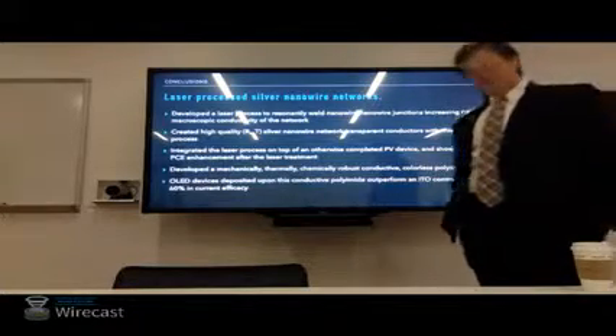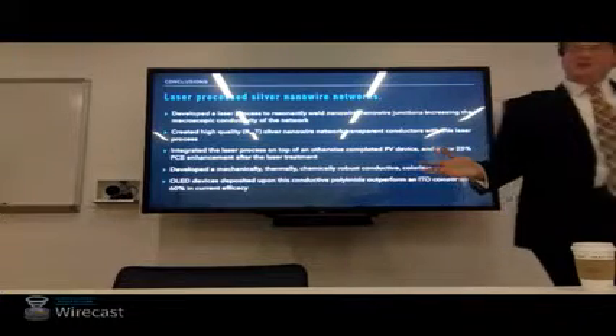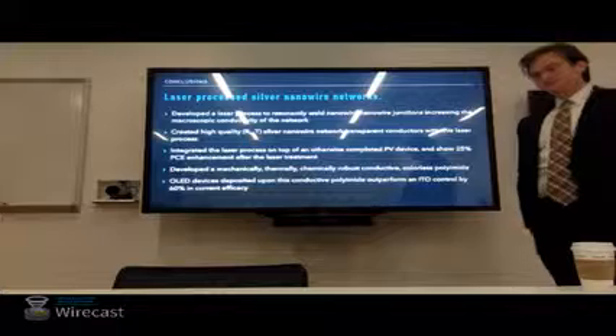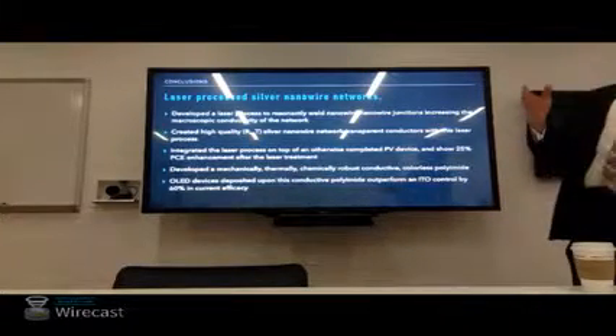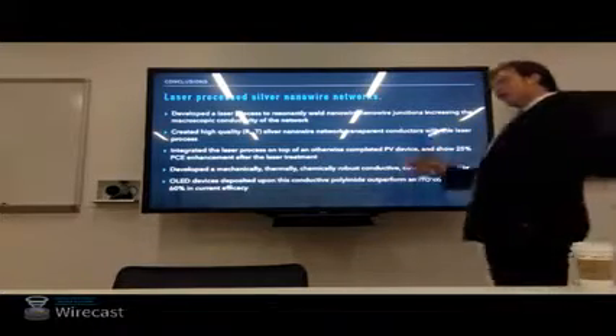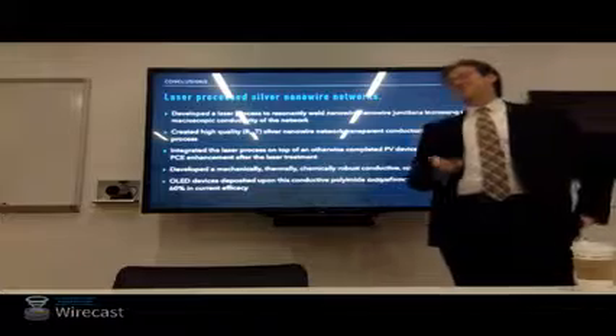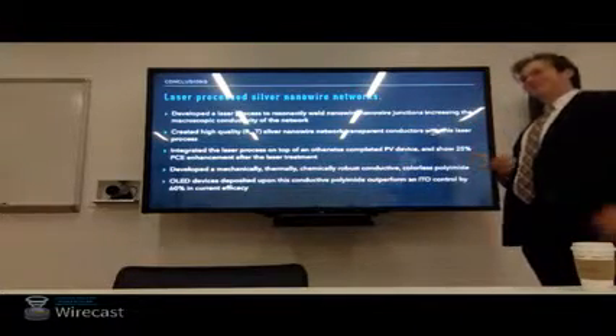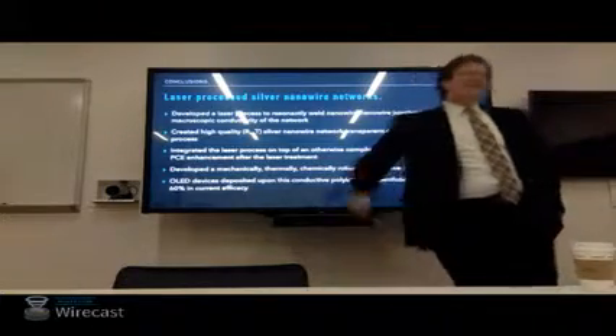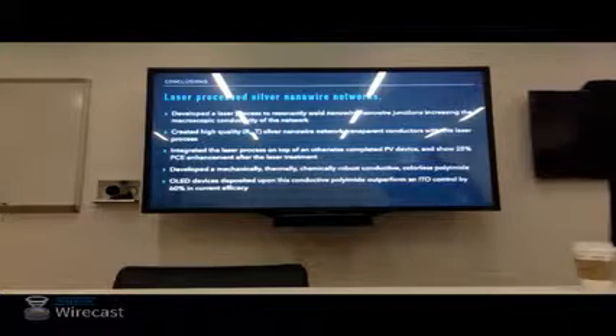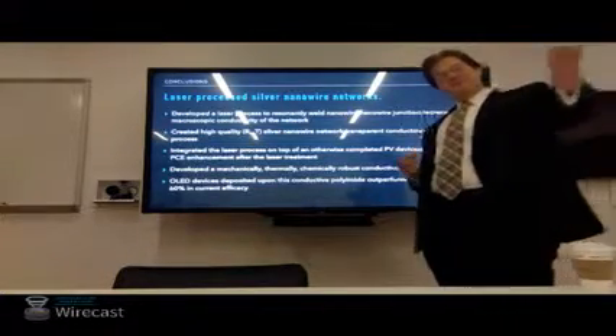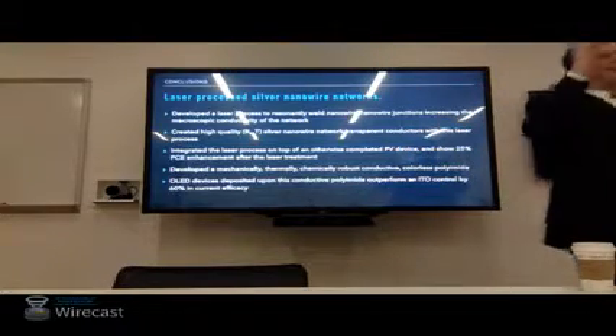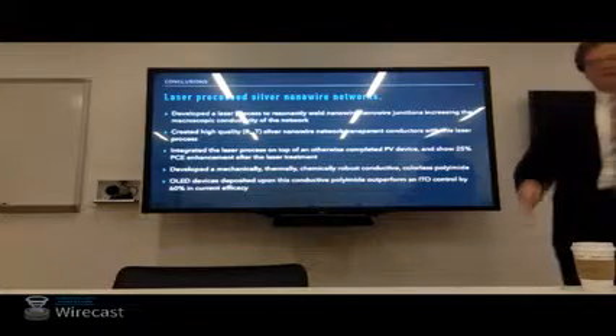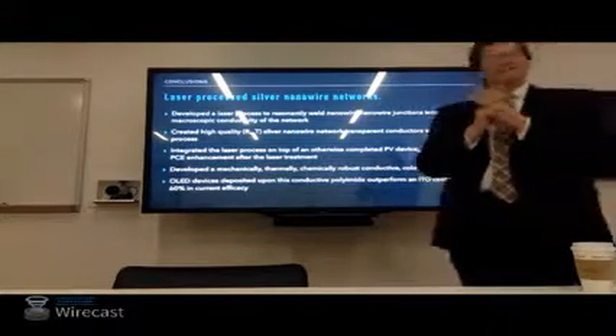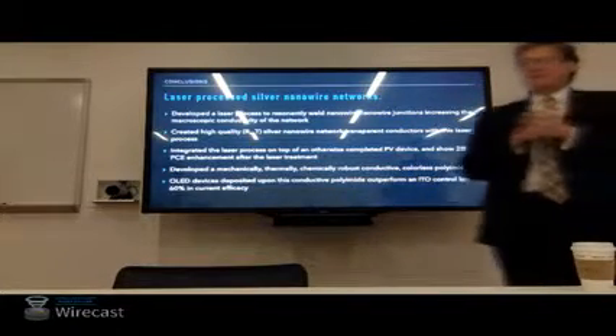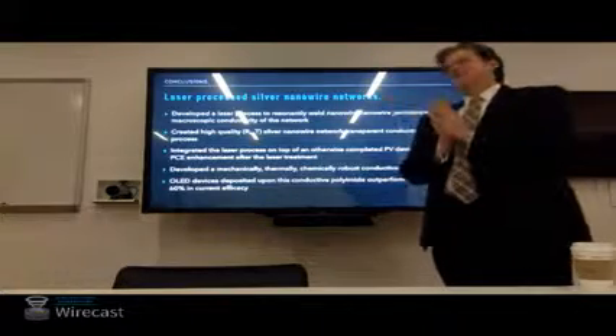Yeah, because the real-world analog, as you just pointed out, is not just our nanowires. There are nanoparticles in there, and there's probably solvent residue, and crud, which is ubiquitous. Ubiquitous crud as well. One of the main harping points I put up in the beginning is that we make these electrodes in the lab atmosphere, we laser process them in the lab atmosphere, which sounds wonderful until you introduce ubiquitous crud. That makes me jealous of people who do vapor phase deposition because they get the high purity. The vapor phase deposition people would look at me and go, do you know how often I have to refine my ingredients? And then if something goes wrong, I have no idea what the contaminant was. So there might be a happy medium, but I get the benefits of working in the laboratory atmosphere, which certainly come with the detriments of things like crud.